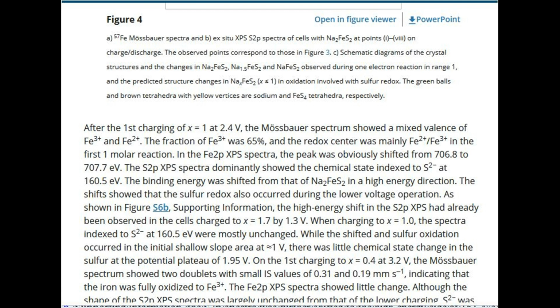As shown in figure S6b, supporting information, the high energy shift in the S2p XPS had already been observed in the cells charged to x = 1.7 by 1.3 V. When charging to x = 1.0, the spectra indexed to S2- at 160.5 eV were mostly unchanged. While the shift and sulfur oxidation occurred in the initial shallow slope area at 1 V, there was little chemical state change in the sulfur at the potential plateau of 1.95 V.